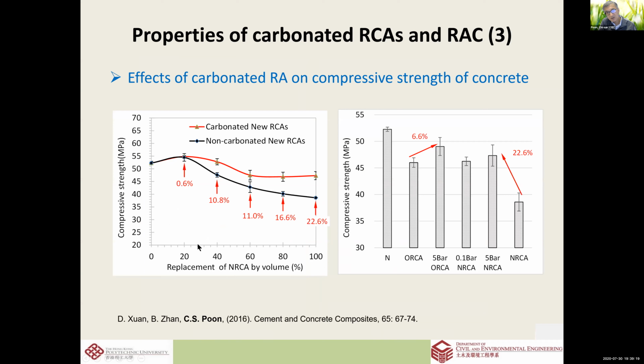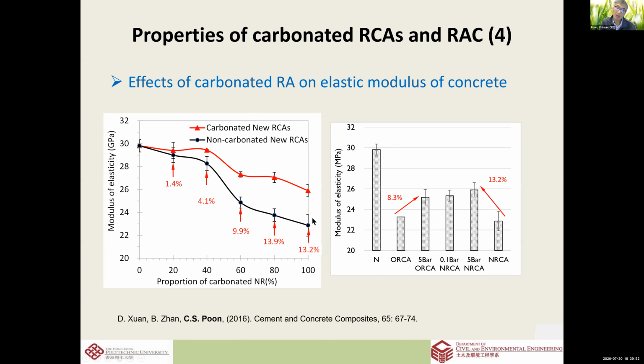So we try to make use of this material to make new concrete. We just concentrate on using 100% recycled aggregate to replace natural aggregate. This is without carbonation, and this is with carbonation. And then we see that there's some 20%, 22% increase in compressive strength when we make use of the carbonated aggregate. And also for the mortars, there's about 10 to 15% improvement.